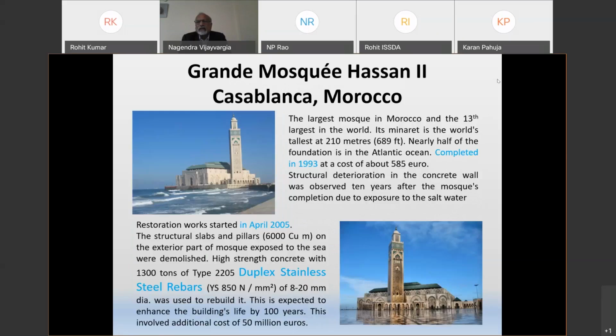Now it is an example that if at the beginning itself we use proper material, then there should not be any problem. This mosque in Morocco was built in 1993 at a cost of €585. And structural deterioration in the concrete wall was observed just 10 years after it was built. So restoration work started in April 2005. The structural slabs and pillars on the exterior part of the mosque exposed to the sea were demolished, and 2205 duplex stainless steel was used, with 1,300 tons used to rebuild the pillars. And now they expect that it will have a 100-year life.